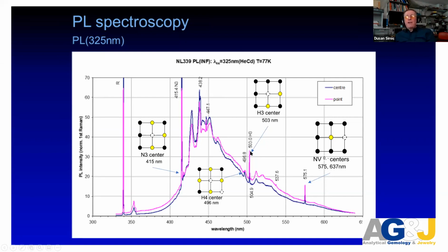H4, H3: if you see the H4 center, you will say this stone was not touched with temperature, because the annealing temperature for the H4 center is about 500 Celsius. You can anneal this center just when you are polishing and the temperature increases even to 500 Celsius, and also the NV centers.